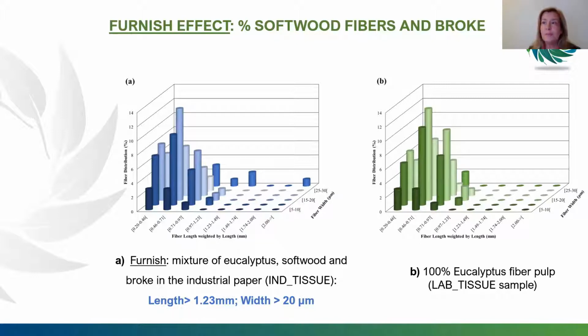But as we know, the industrial pulp is made with a mixed blend of softwood pulps and has a certain percentage of an internal recirculation pulp designated as broke. On the left side, image A, we have the industrial paper sample biometry. We can observe that we have fiber lengths bigger than 1.23 millimeters and widths bigger than 20 micrometers, which are indicative of the presence of these softwood fibers.